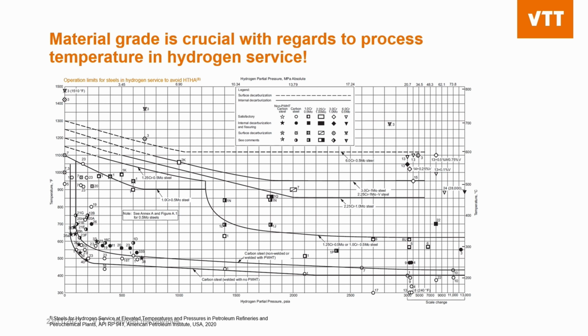If we look at the lowest curves, we see that they are plain carbon steel materials welded with or without post-weld heat treatment. And when we go upper in these curves, we see that there are alloying elements such as chromium, molybdenum and vanadium in these steels, which improve their resistance against the high temperature hydrogen attack.